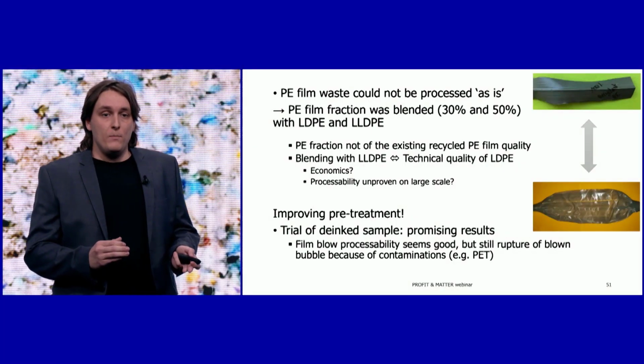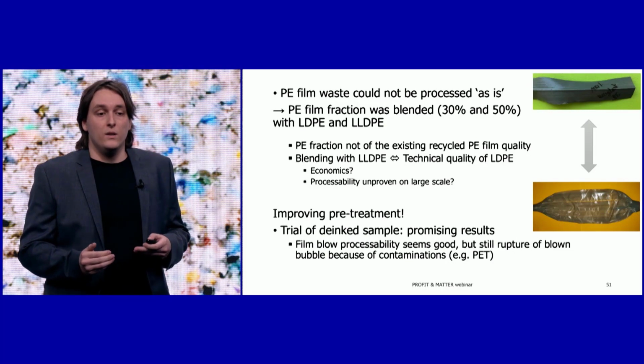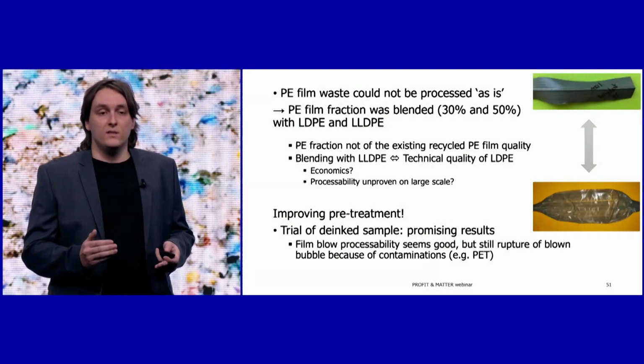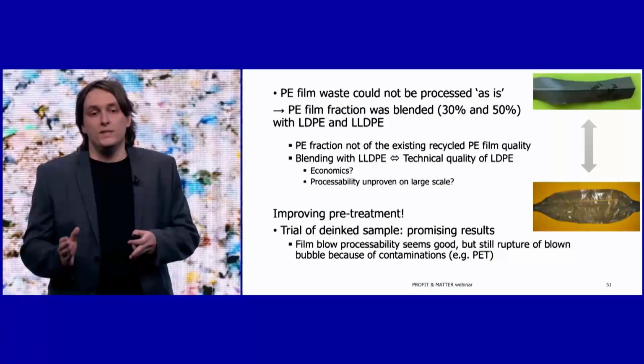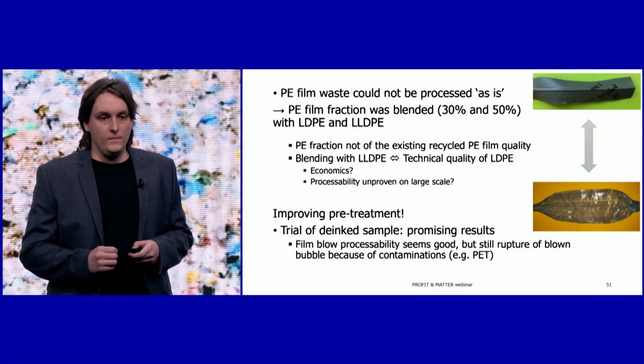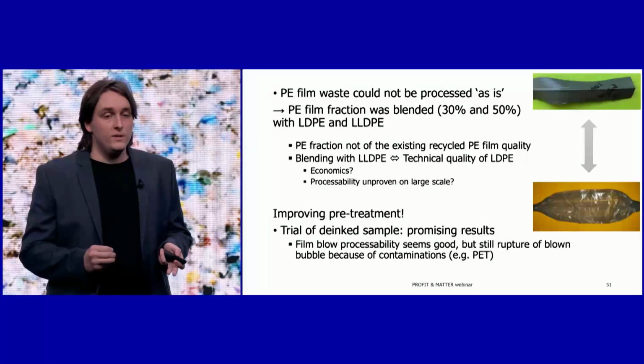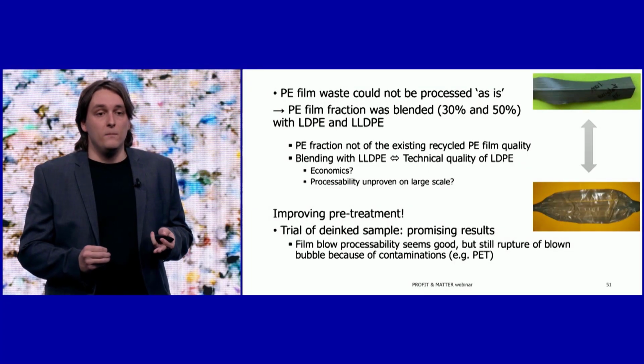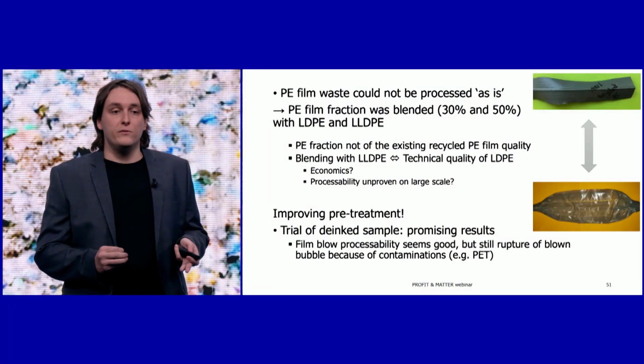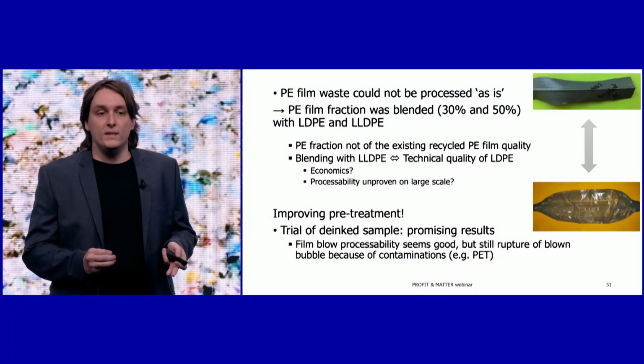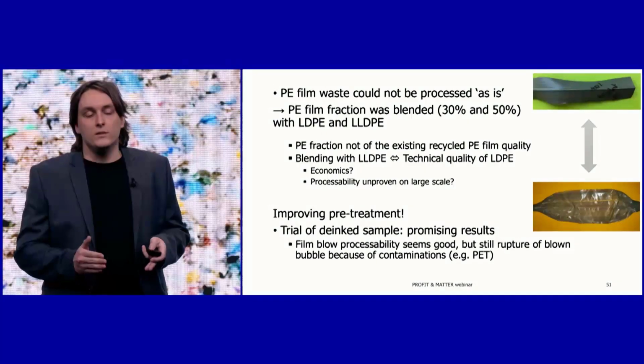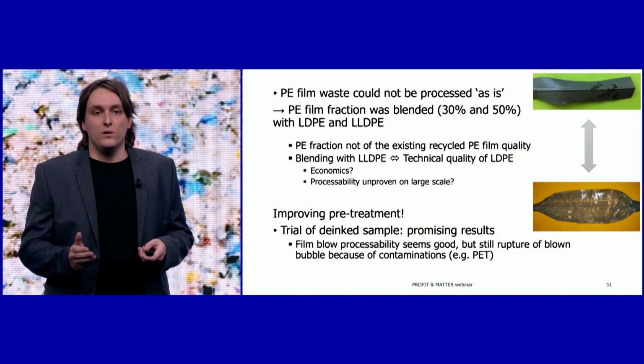For the de-inking step, we did a trial on a de-inked sample to see the positive influence on this processing. The film blow processing seems to be better, but it still contained a lot of contaminants that are not melting, and these non-melting contaminants cause rupture of the PE films.